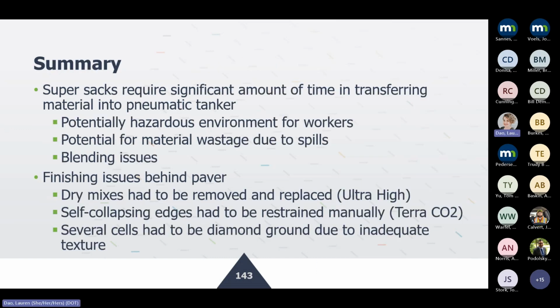And in general, the one main issue with constructability was that a lot of these materials came in huge super sacks, and they take a lot of time in getting transported to pneumatic tankers, right? And it presents a potentially hazardous environment for the workers, and you could also waste a lot of material with spills. A lot of these mixtures did have blending issues, and I did have to note that. And there were finishing issues behind the paver, and dry mixtures we had to remove and replace. Then there were some self-collapsing edges that had to be restrained manually and refinished at the end. And as we noted earlier, several cells had to be diamond ground to attain the desired texture.